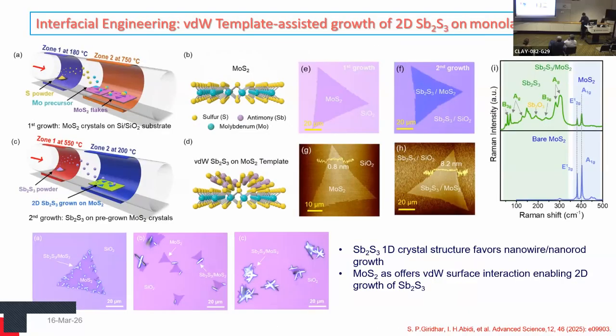Then we use MoS2 to grow another 2D material on top of it, which in this case is Sb2S3. Sb2S3 is a 1D material, and it's normally hard to grow in the 2D lateral direction. So in this case, we use MoS2 as a template, which has van der Waals surfaces. So these van der Waals surfaces attract another layer on top of it, so it will grow the second layer on top of it in the 2D form as well.